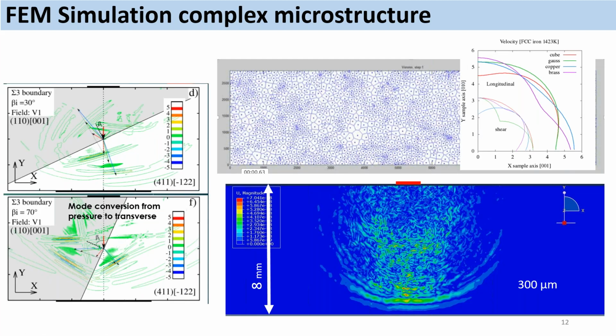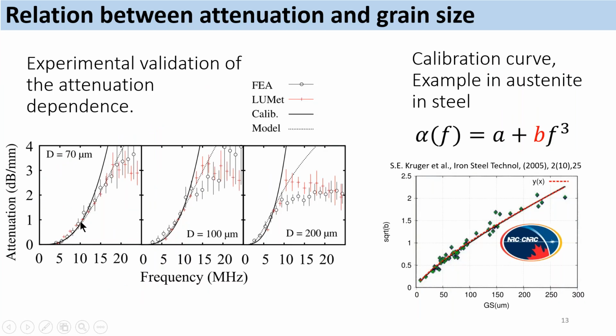So if we were to try to validate those theories from simulation, we can build some microstructure using finite element microstructure. We can create some microstructure, attribute properties to each grain, those elastic properties, which, reminding ourselves, are anisotropic in metals. And we can then build some attenuation spectrum that we can see here. So I have shown here in comparison the attenuation spectrum that we can measure from the finite element analysis and the attenuation spectrum that we can measure in Lumet, and you can see here that there is a good correspondence between those two. So here we can reassure ourselves that those theories, here in dashed line, are actually in very good agreement with the measurement that we can do in Lumet. We can validate as well some complex microstructure using some simulation tools.